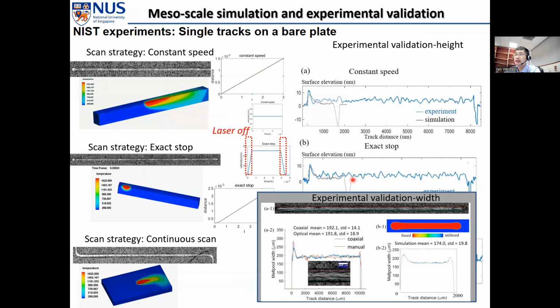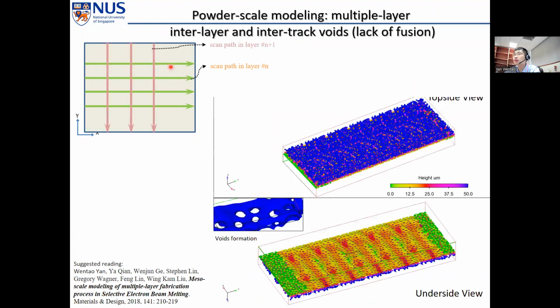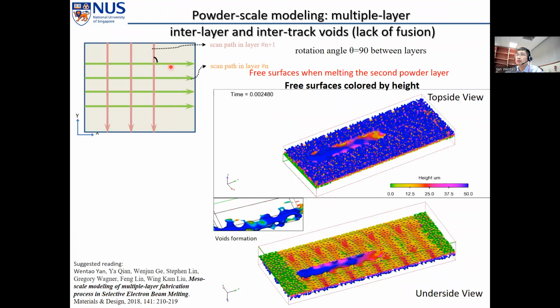And also we validated our multiple welds that's here. And you can see there is a large peak in the beginning and a small peak in the ending. And our simulation can reproduce both peaks, and also we can compare quantitatively the mean value and standard deviation, and they all agree well between simulation and experiments. And for more complex cases, like multiple layers, multiple tracks, this is a reason how the interlayer, intertrack voids will be formed. So no matter what the scan path is in experiments, maybe like this in one layer and the next layer it will turn a certain angle, we can well reproduce it in our simulation.